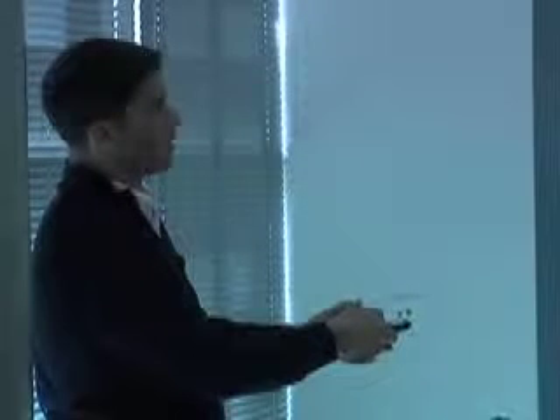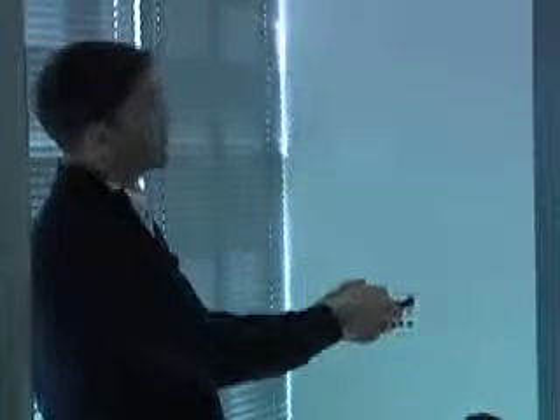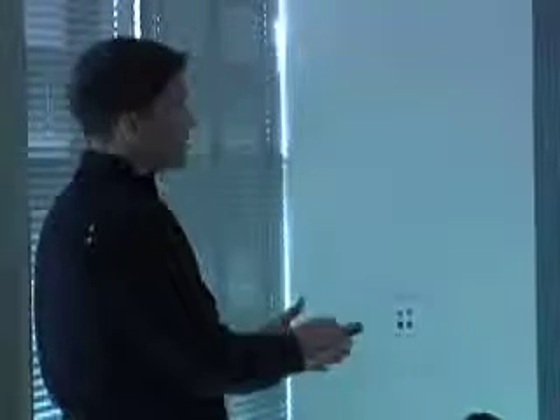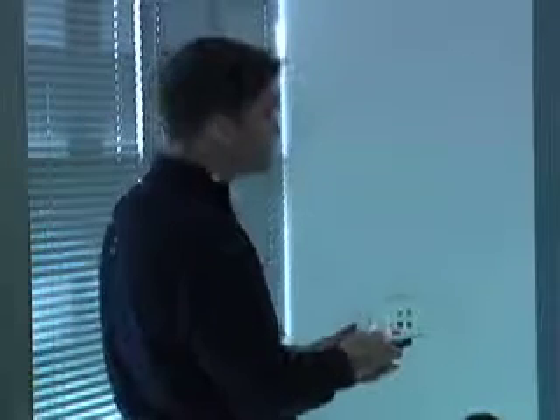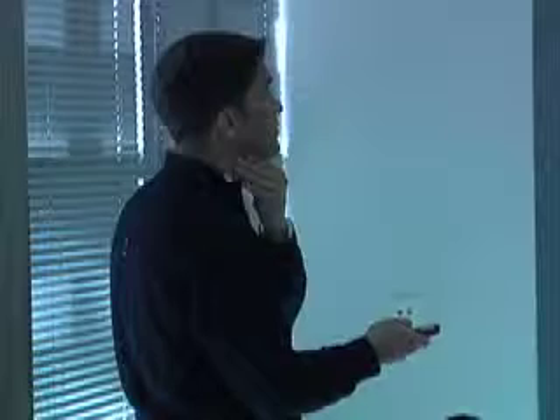We've also been working with another thiophene backbone polymer from Zhenan Bao's group, and you can see with that one, we can get up to a full 1.1 VOC just in a single cell device. I think that's pretty interesting. And we've been plugging away through this, and again, this non-planar naphthyl imide is still operating in this sort of 0.2% range. So this is, I think, one of the highest non-fullerene OPVs to date.